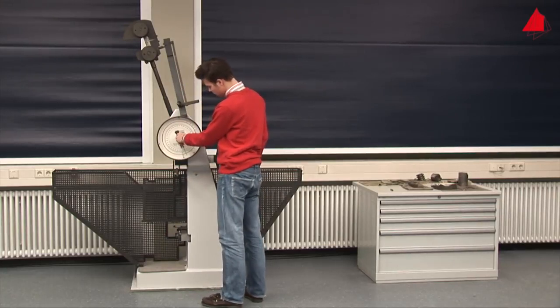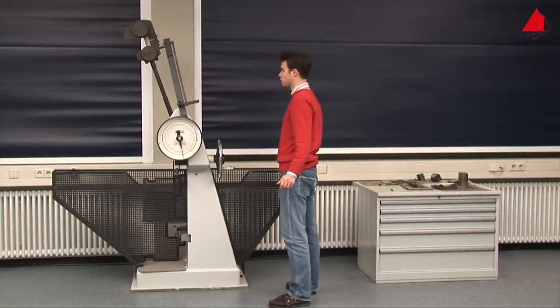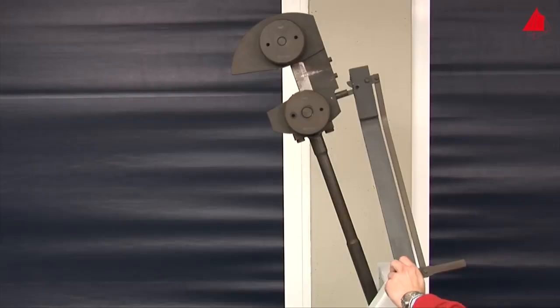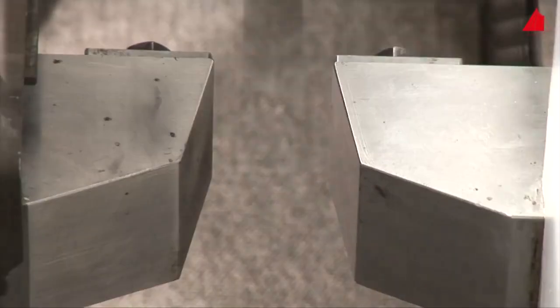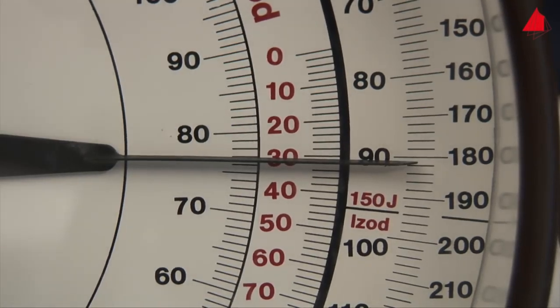The tester turns the drag indicator to its starting position, rechecks all safety measures and releases the pendulum. This time the impact sounds much deeper and richer. An impressive energy of 182 joules has been absorbed by the specimen.